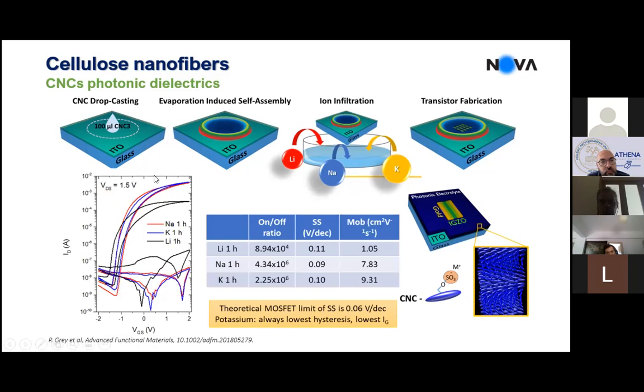And we can also use these membranes as a dielectric in transistors. Here the gate electrode, the ITO layer, is on top of glass. We put these membranes on it and then we make the devices on top of the membranes. And you see, again, the voltage window is very narrow, and the hysteresis was also in the range of some millivolts.